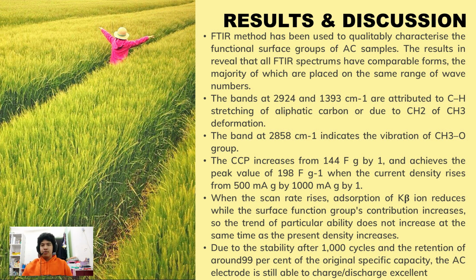FTIR has been used to qualitatively characterize the functional surface groups of AC samples. The results reveal that all FTIR spectra have comparable form, the majority of which are placed in the same range of wave numbers. The bands at 2924 and 1393 per cm are attributed to CH bond stretching of aliphatic carbon or due to CH2 or CH3 deformation. The band at 2858 per cm indicates the vibration of the bonding CH3O group.